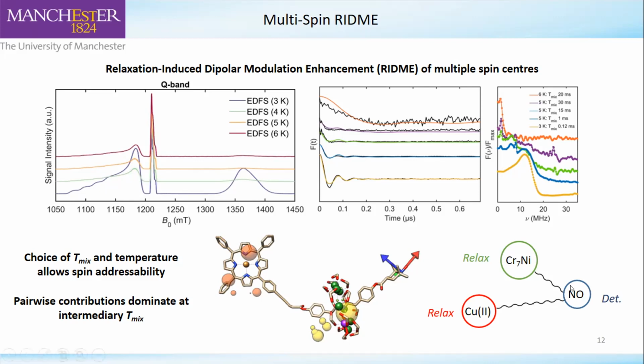So we can look at either the interqubit interaction between the nitroxide and the chromium-7 nickel ring, or the interqubit interaction between the nitroxide and the copper. And again, we could model, based on our simulation library, where that copper spin is going to end up relative to our nitroxide spin when we're detecting here in our RIDME experiments.